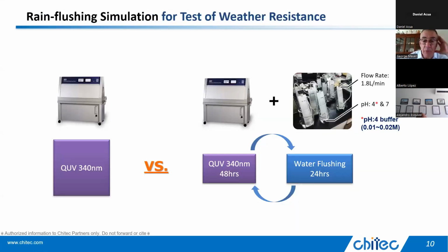Okay, one of the things that we always found curious was 1130 in a weatherometer or in a QUV seemed okay. It was never the best, but it was usually pretty decent and certainly much better than a blank that had no UV absorber. But out in the field, whether it's in Florida or Taiwan, where Chitec is based, they have harsh environment there. Or Okinawa is a common test site for the Japanese auto manufacturers, or Australia. In those areas, and actually Acapulco for some people has been used as a difficult exposure site. The 1130 never performed well in those exterior sites, so we were sort of wondering why.